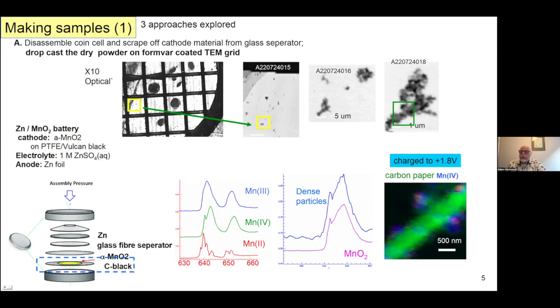And in this particular case, which was the as-made fully charged battery material, they're all in the manganese 4+ state. So yes, that in some sense confirms that, but we have so little oxide material there, it's not very much of a convincing story. So having done several tries at this at various synchrotrons, we decided that we would really go back to the tried and true method of embedding and microtoming.